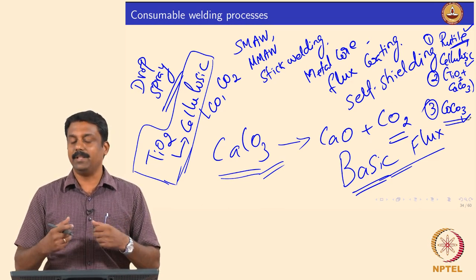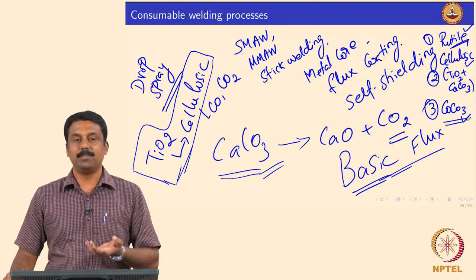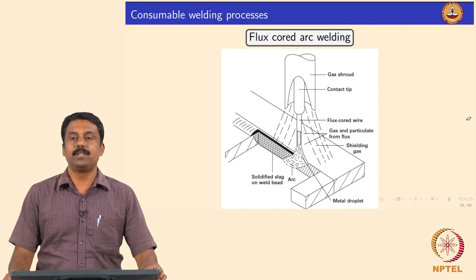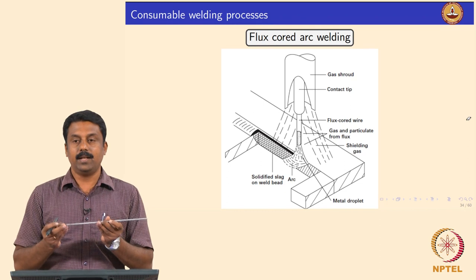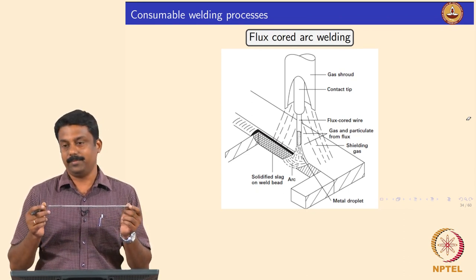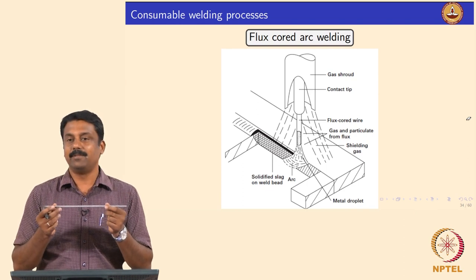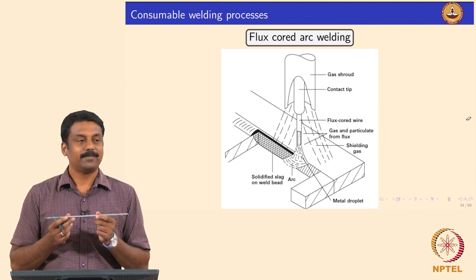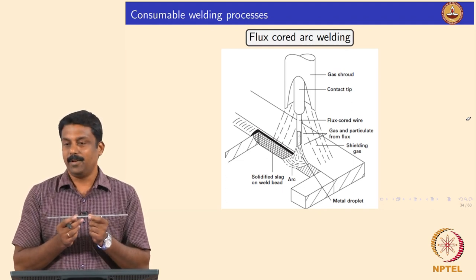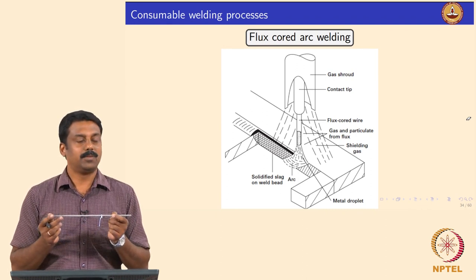We will look at the role of fluxes in detail in both SMAW and FCAW, and also look at videos of how the metal transfer takes place when these fluxes burn. In SMAW, the electrode has a metal core with flux coating on top. The electrode shown here is a basic flux electrode — calcium carbonate based. If used right away in a humid environment without baking, it would definitely lead to cold cracking.